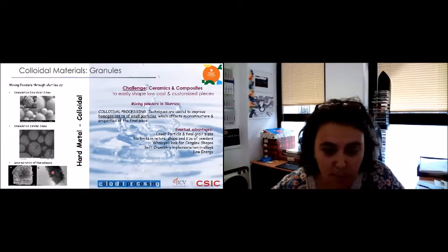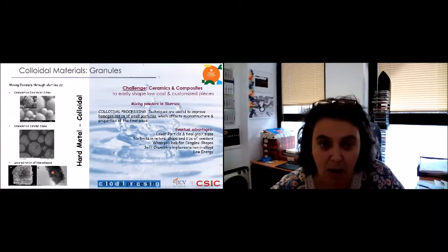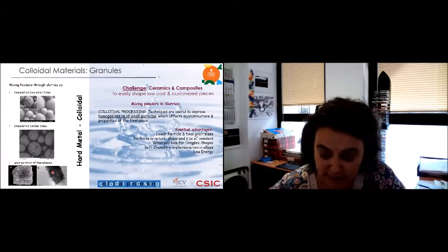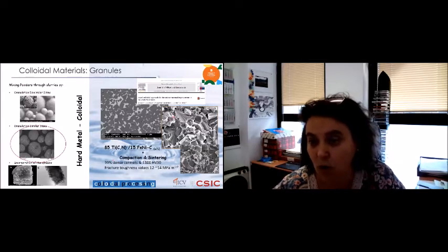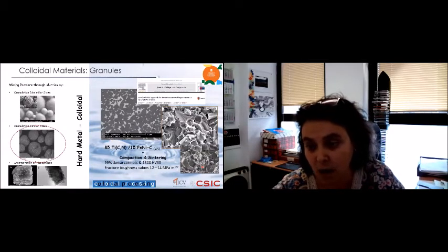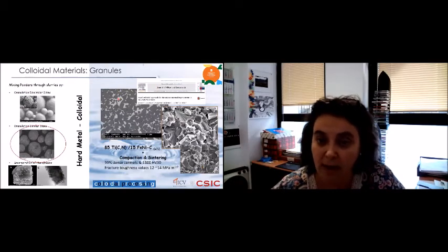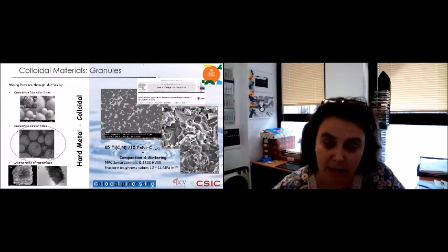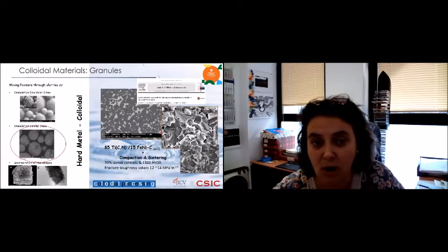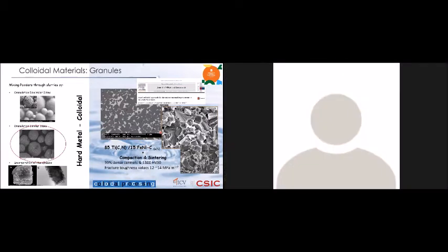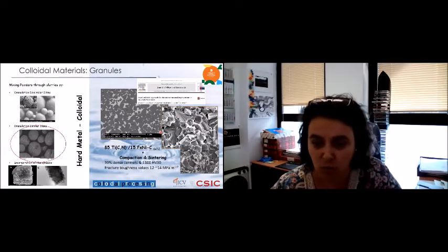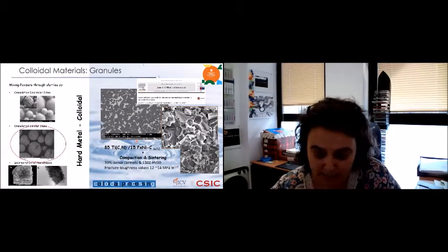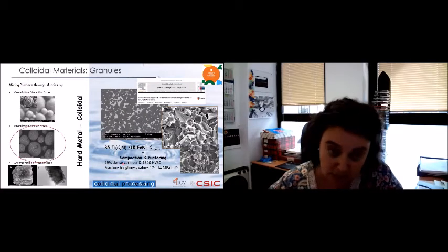In this way, you are preparing the feedstock of your additive manufacturing technique, just to have a very coherent microstructure at the end of your work when you arrive at the sintering, right? And have all the two phases. In this case, it is a titanium carbonitride and iron nickel alloy mixing together, and to have a well compacted microstructure that works very well in this application, right?